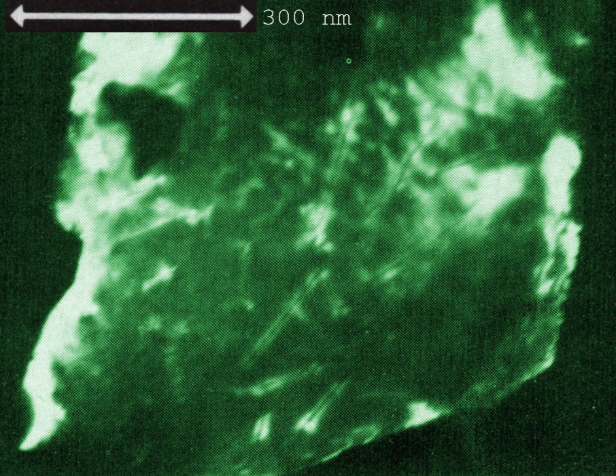Surfactant-enhanced etching. Surfactant-enhanced etching is used to modify ion track shapes. It is based on self-organized monolayers. The monolayers are semi-permeable for the solvated ions of the etch medium and reduce surface attack. Depending on the relative concentration of the surfactant and the etch medium, barrel or cylindrical-shaped ion track pores are obtained. The technique can be used to increase the aspect ratio.